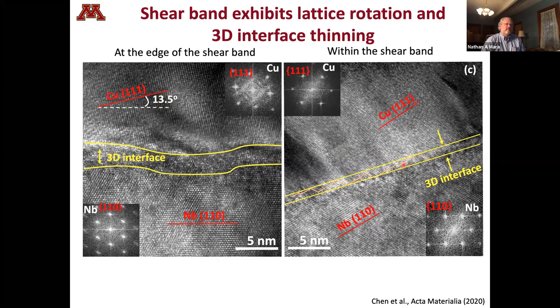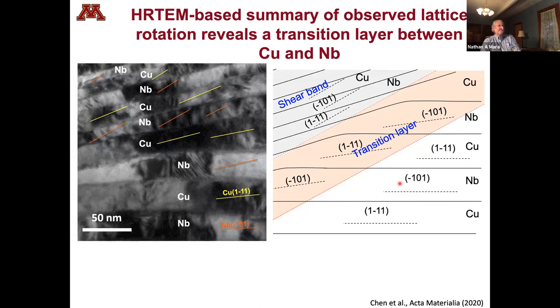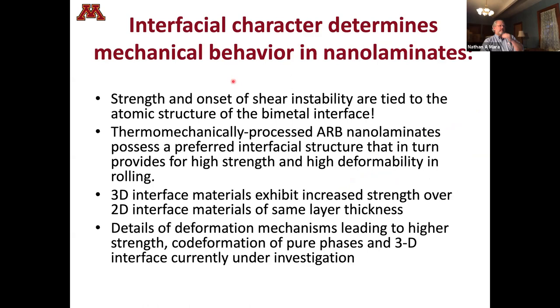So we're currently working on trying to figure out how this transition layer actually stacks up with the rest of the material. This is work that's still in progress. But what we have are data sets of all of those high resolution TEM micrographs in these different regions. So if you do 1, 2, 3, 4, 5, about 12 different TEM micrographs, you can actually quantify the degree of rotation you're getting as a function of position. And so we're still working towards this. So that sort of summarizes what we've got for the 3D interface portion here.